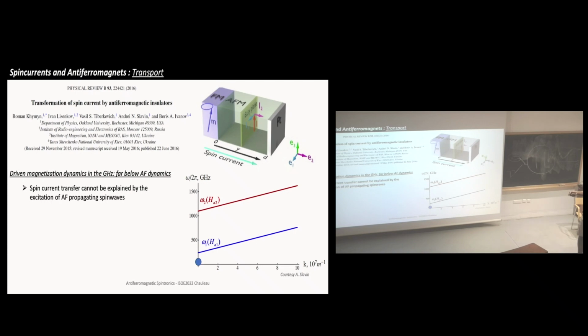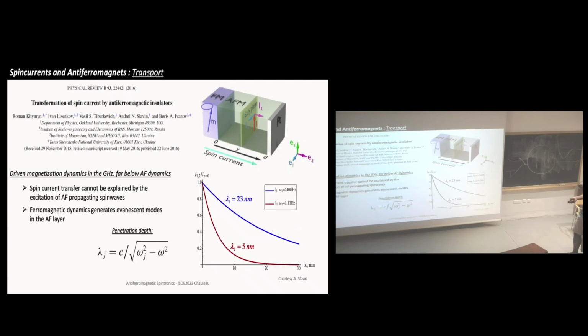And actually, there was this work from André Slavin and his co-authors, who tackled this one. Fair enough, you excite this very far away from the two resonance frequencies, so you have the two branches, but it's not a problem. You will excite waves, but they will be evanescent modes. You cannot convey them over microns, but there will be evanescent modes with a penetration depth of this form. For NiO, one has a penetration length of 23 nanometers, the other one 5 nanometers.